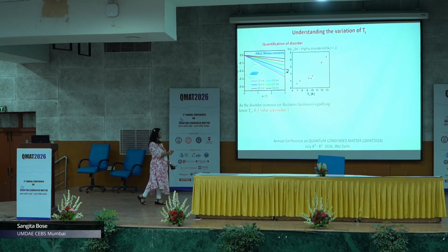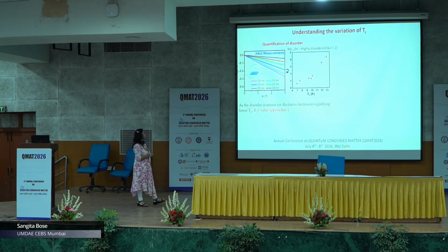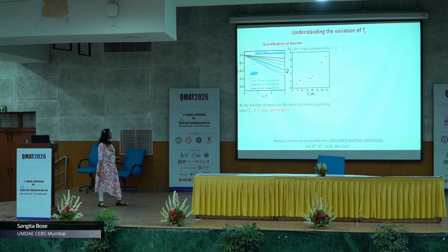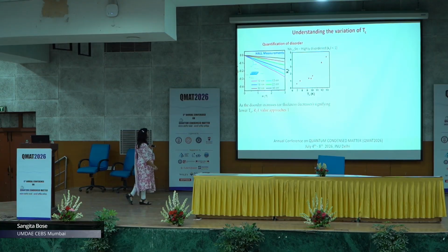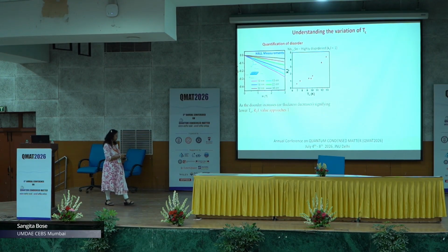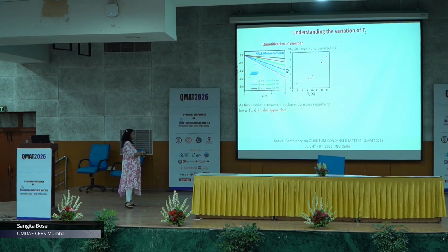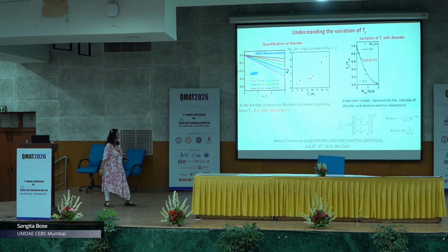It is well known that this parameter kFl is a measure of the disorder strength. It is usually taken as the measure of the disorder strength in the community. So, you can measure this by doing Hall measurements, and that is what we did, and this is kFl as a function of Tc, and you see that kFl decreases, and for our thinnest film we actually go to kFl values which are even less than 1. So, for people who might know that kFl approaching 1 gives the very strong disorder regime, we conclude that we are actually entering a very strong disorder regime in these systems.